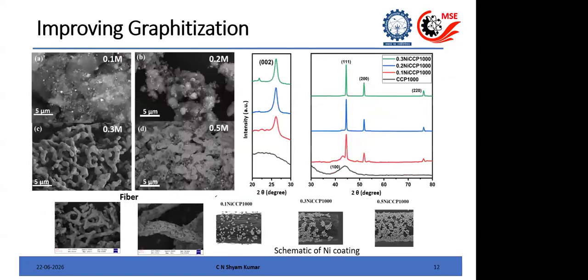And also on top of that, we have a very fine nickel particle which is dispersed all over the carbon. So basically you have a nickel carbon composite with a one-step synthesis. And this is one more characterization technique that we use, XRD. XRD is used to understand the improvement in the graphite content also.